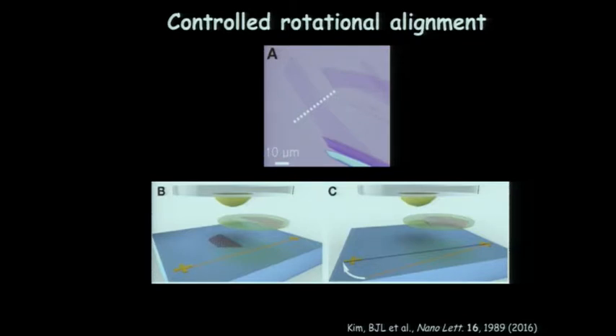And so this was work done in Emmanuel Tutuk's group, developing this technique to make these heterostructures where we can have a controlled twist between the 2 graphene layers. And since they're coming from the same graphene flake, we know precisely what the angle is just by how much we rotate the stage between the two transfer steps.